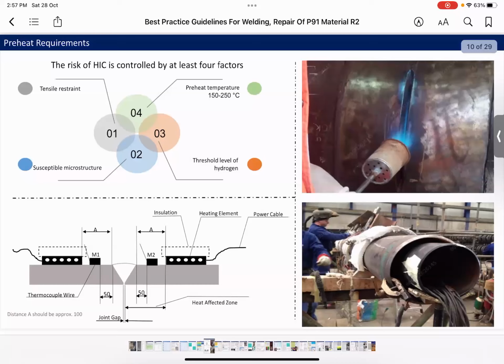It should be done using ceramic fiber blanket, and it should be monitored by thermocouple according to the illustration shown here. So the distance between the thermocouple and the edge of the weld is 50, and an element to the weld is 100 mm. This is to give proper access to the welder. And of course, if you have access from the ID, thermocouples should be installed from inside as well.